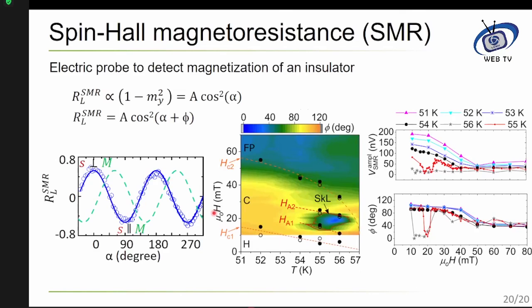If we measure such resistances, we can get an amplitude and a phase by fitting these curves, and we can plot them in a color plot. Here, each color is a data point from such measurements. You can see the phase is varying from 0 to 120 degrees. Here is the magnetic field, and here is temperature. What it tells you is that at large magnetic field, the angle between the magnetic field and the magnetization is 0, meaning everything is aligned with the field. As you go down, the angle between the magnetic field and magnetization starts to increase.